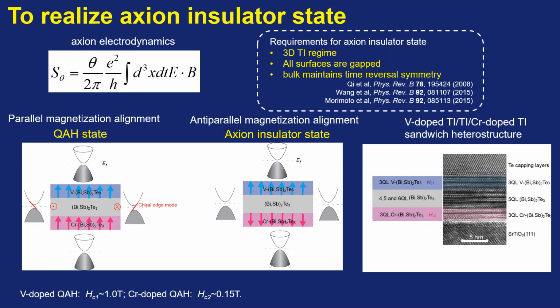So we are thinking to fabricate this kind of quantum anomalous Hall sandwich structure. The bottom layer is 3 quintuple layer chromium doped bismuth antimony telluride. The top layer is vanadium doped bismuth antimony telluride, and the middle layer is 5 quintuple layer bismuth antimony telluride. So at very high field, if the magnetization of the top layer and bottom layer are parallel, we will realize the quantum anomalous Hall effect. There is the chiral state.